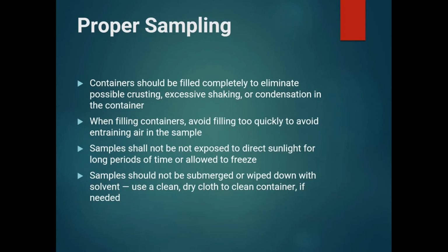When filling up the containers, they should be filled completely to eliminate possible crusting or skinning of the emulsion that can show up as sieve when it gets to the lab, excessive shaking from having a lot of empty space, or condensation in the container. When filling the containers, you want to avoid filling them too quickly because you may entrain air in that sample. Also, samples should not really be exposed to direct sunlight or allowed to freeze.